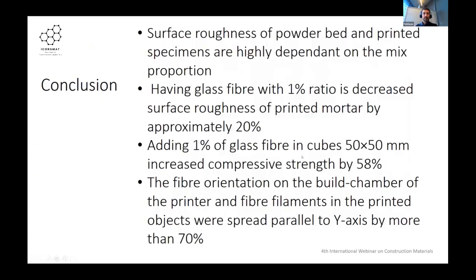Another point we need to check is the overall surface roughness of the printed material, which should be considered because it really affects the mechanical behavior of the materials. If we are printing any kind of material with different properties, we get different results. Because it is a cementitious material, it's not just cement; we are using sand and another kind of accelerator, so most probably the surface roughness changes. But having glass fiber is really helpful. I highly recommend changing this ratio to a different ratio, and we may get different results.